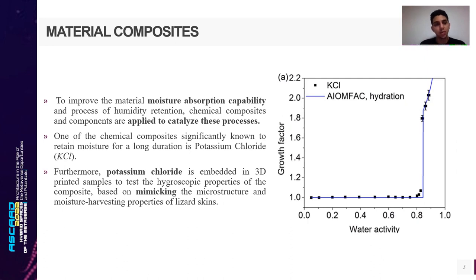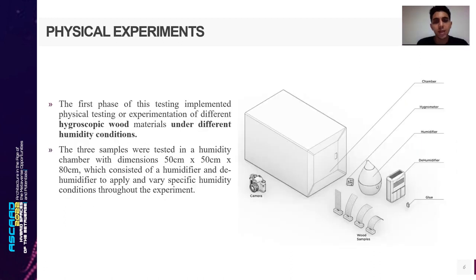Chemical composites and components are applied to catalyze the process of humidity retention to improve the material's moisture absorption capability. Potassium chloride as a chemical composite can also retain moisture for a long duration. Based on mimicking the microstructure and moisture harvesting properties of lizard skins, potassium chloride is embedded in the 3D printed samples to test the hygroscopic properties of the composite. Under different humidity conditions, the hygroscopic wood materials have been experimented on.